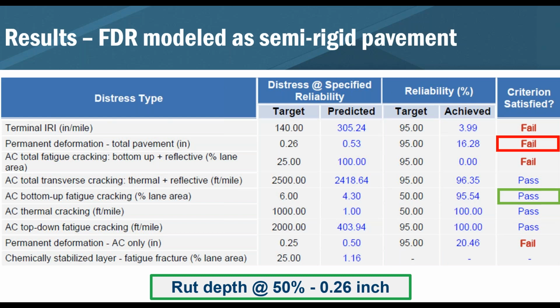Also, the bottom-up fatigue cracking passes. It's actually quite low. The target is 6, and the predicted value is only 4.3. And then, of course, the asphalt rutting is predominantly what's driving the total rutting. So it is all pretty much in the asphalt layers, and very little of it is in the underlying layers.